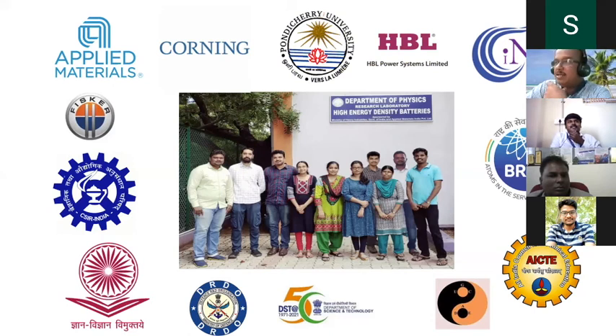It has all the characteristics. But my rule of thumb, from almost 14 years of my battery research, is that if you have one or two good properties, certainly you will have others diminished. It's very, very difficult to get sulfides and process them at ambient or open air conditions. And whatever results they get in button cells, coin cells, they cannot reproduce when they move to pouch cells. That's why Toyota is spending huge money, but still, when you go for bulk production, even the electrolyte conductivity has come down again.